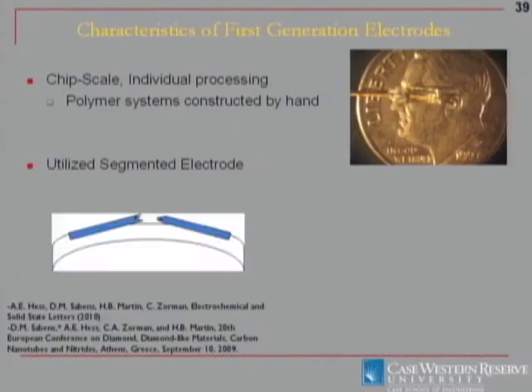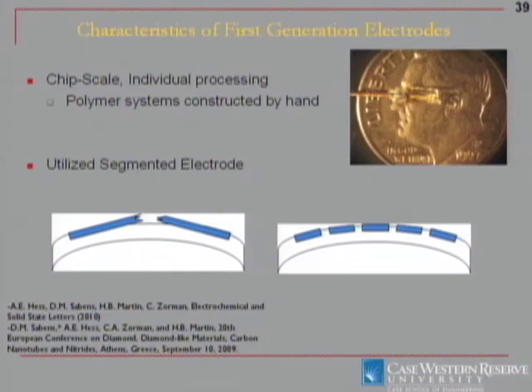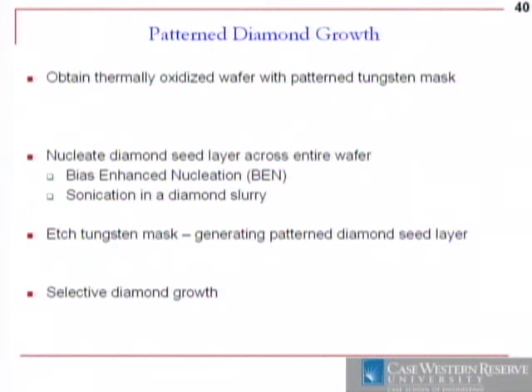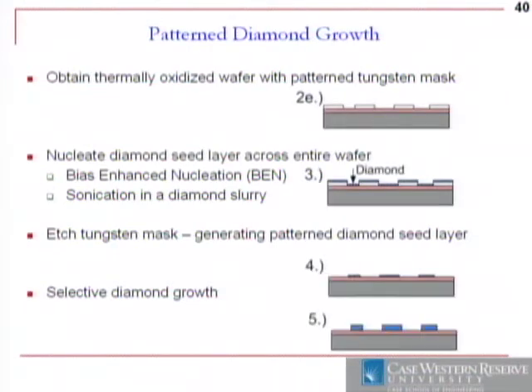So what are the characteristics of this? One of the ideas here is, again, diamond is a brittle material, and if we use a large electrode, it may break. So we've got a design here that has a segment electrode approach, which has small pads that are combined to form possibly 1 larger electrode. The first generation we did was making individual electrodes at a time, where we were focusing more on the idea of transferring and not on all the microfab to incorporate the metal contacts, but we'll get to that. I better skip through this because I'm running out of time. But we have a selective diamond growth process developed by David Sabens, where we actually deposit the diamond with a metal mask present.